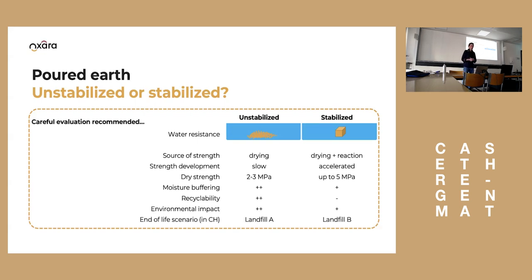That's a drawback. And then on the environmental impact, clearly the unstabilized one has the lower CO2 footprint. For the stabilized one, it really depends on the stabilizer that you use and the dosage. And for the end of life scenario, if you have raw earth or one with a very low percentage of admixture, it is landfill A. So if it's unstabilized, and if you stabilize it, then it counts as a construction material, which needs to go to landfill B.